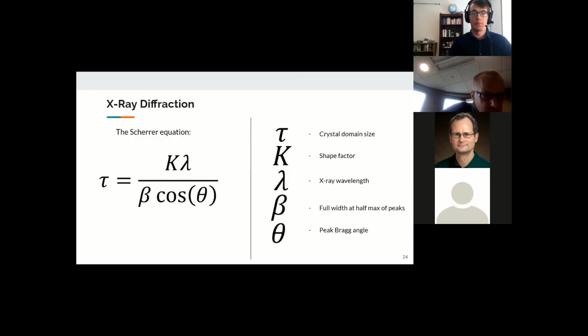Further confirmation of the beta structure of the powder is found using XRD. And XRD can also be used to find the size of the particles through the Scherrer equation, which is displayed here. In this equation, tau is the mean size of the ordered domains. K is the shape factor, which was taken to be 0.94 for spherical crystals with cubic symmetry. Lambda is the X-ray wavelength. Beta is the line broadening at the half maximum intensity, and theta is the Bragg angle.